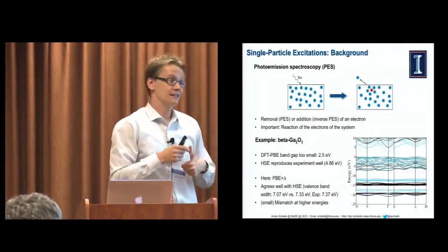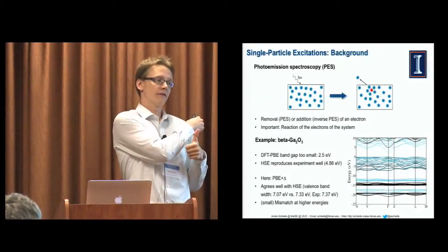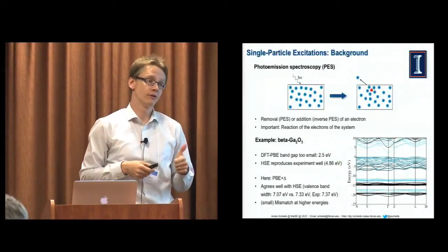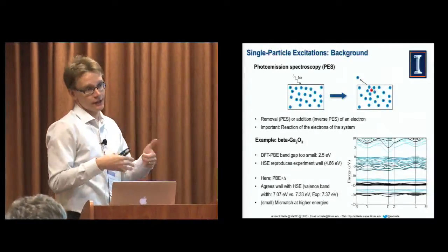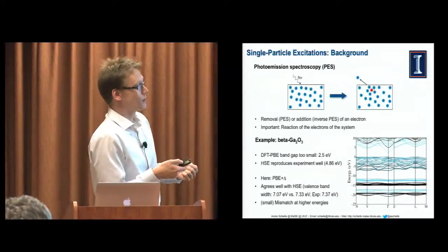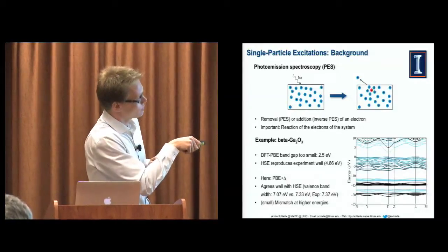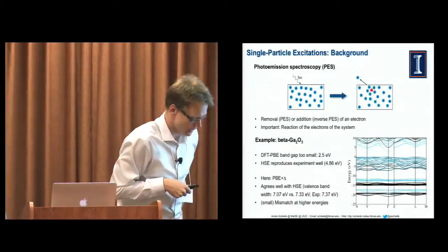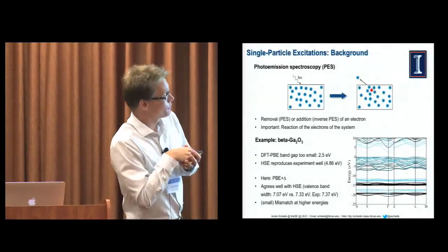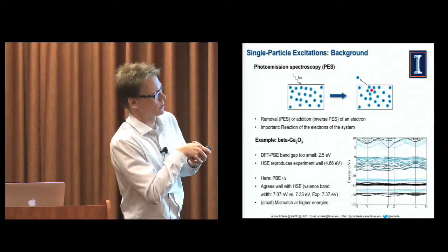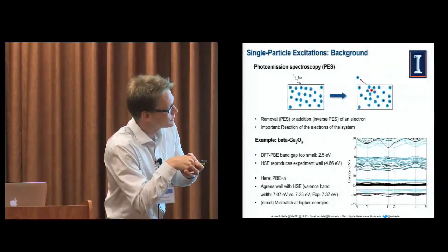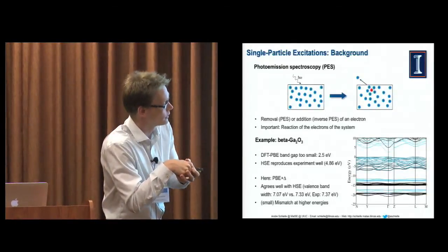The problem is that density functional theory, that approach that I talked about in the very beginning, does not do a good job in calculating these quantities. And so we have to go beyond. And so now one example of that is shown down here. Unfortunately, you can't really see these blue lines very well. So if we did density functional theory for gallium oxide, what you get for the band structure is these blue lines here, right, and all the other ones in this plot.